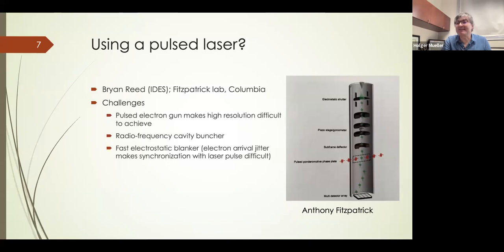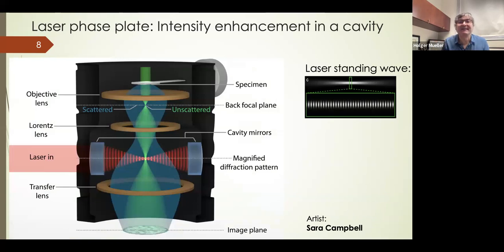So instead of tackling these issues, we decided to use another method that my lab was very familiar with, using a Fabry-Perot cavity to build up a lot of intensity from a reasonably powered laser. So here is the principle of the laser phase plate. I want to direct your attention first to the little schematic on the right. If I take a laser beam and confine it between two mirrors, the laser beam can make, for example, 10,000 round trips, building up 10,000 times the intensity that the original laser beam had.